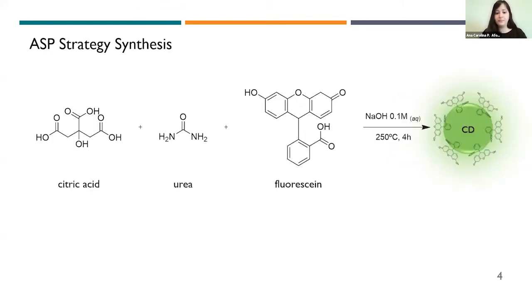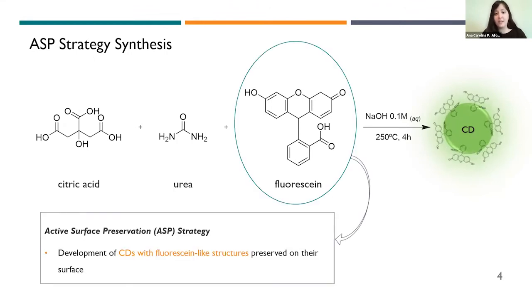Given this, our aim in this work was to use the active surface preservation strategy to rationally develop a carbon dot-based nanosensor with controllable sensing properties. This strategy allows the carbon dots to retain the structural features of the precursors on their surface, making these nanoparticles retain their properties without post-synthesis functionalization. To be more specific, a carbon dot-based nanosensor for pH sensing was developed as proof of concept via the active surface preservation strategy by employing fluorescein as one of the precursors, along with citric acid and urea via a one-pot hydrothermal treatment.